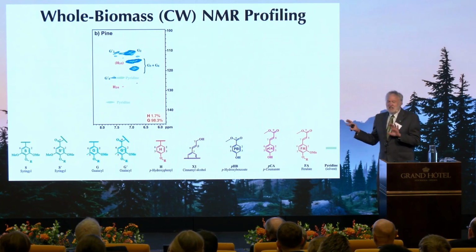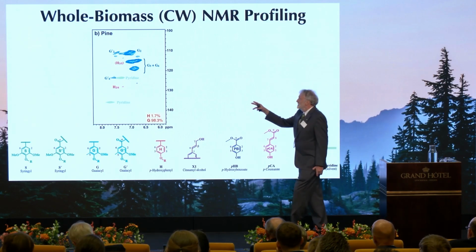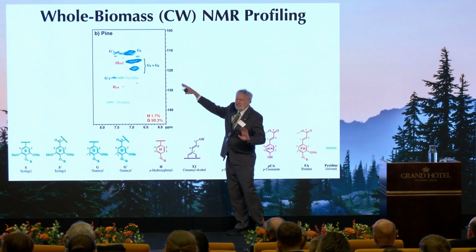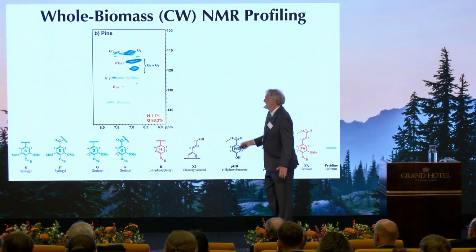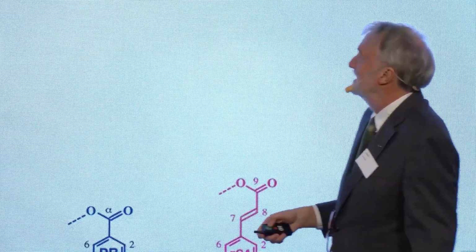So these are in some ways horrible spectra, and yet unbelievably useful profiles of the cell wall components. In the aromatic region, just the aromatics show up. So pine or softwood lignins have just guaiacyl lignins. They have the 3 peaks. I won't go into explaining why that is, but basically, that's the little profile for a guaiacyl lignin.